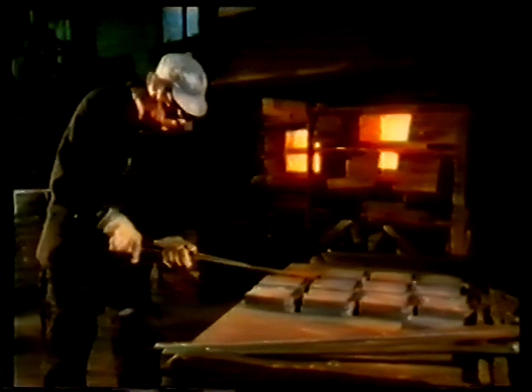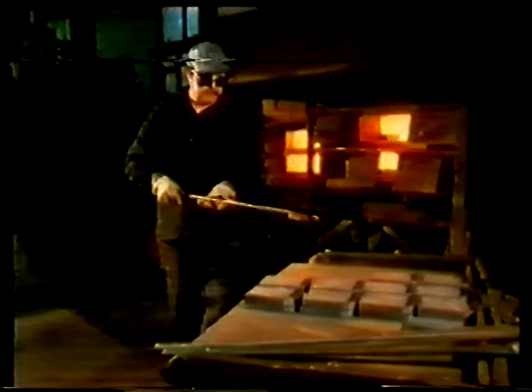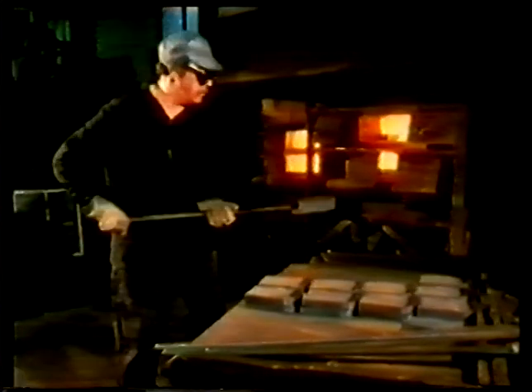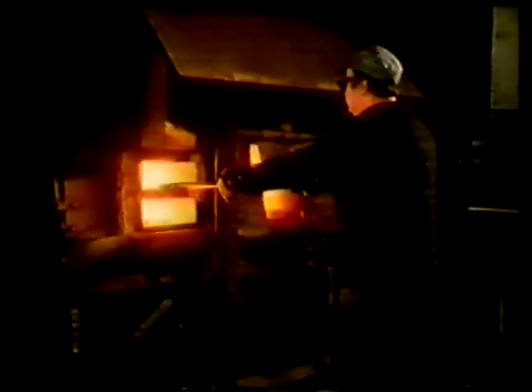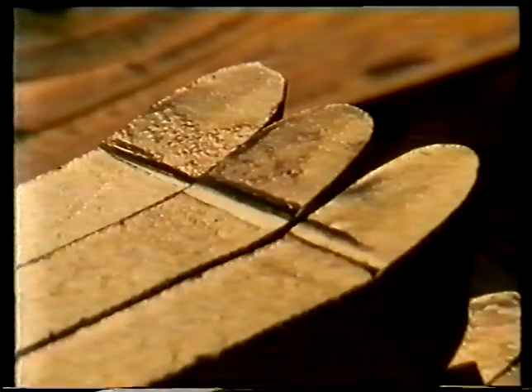Heat treatment is perhaps the most important stage in the production of high-speed steel tools. It's from heat treatment that the tools derive their cutting properties. The first stage is a preheat in which the tools are raised to 850 degrees centigrade. After a few minutes, they're removed and placed in the main chamber at 1200 degrees centigrade for a further period. They're finally quenched in a stream of hot air. Once cleaned, there's one last grinding which imparts a good cutting edge.